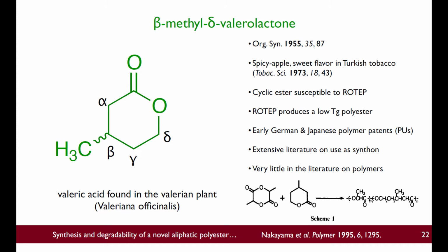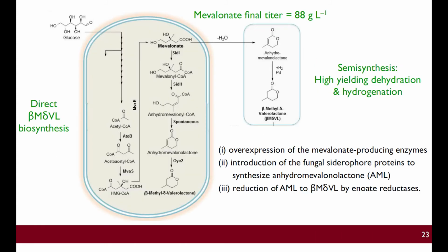And Kachun knew a lot about the mevalonate pathway in microorganisms, and what he did was using these strategies listed over here, he was able to feed a microorganism glucose and generate in the organism beta-methyl delta-valerolactone. In fact, the titer of this was about 0.5 gram per liter, so it wasn't that high, but what he did do is he's able to generate mevalonate at nearly 88 or nearly 90 grams per liter, and a simple dehydration and hydrogenation of that molecule gets beta-methyl valerolactone. So in a semisynthesis that incorporated this metabolic pathway and chemical synthesis, we were able to generate this molecule in very high yield and very high purity.